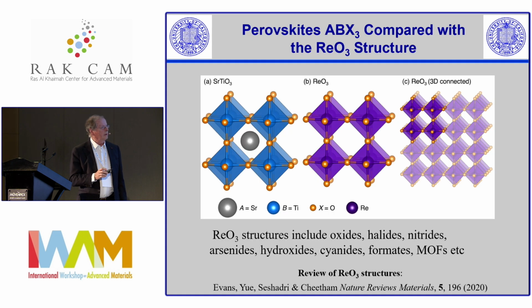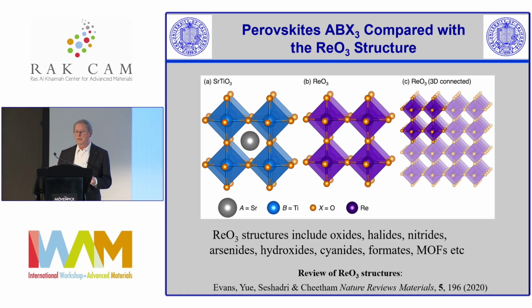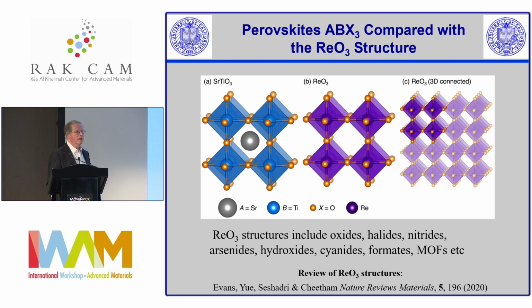So I'm going to switch gear now to talk about the rhenium trioxide type formates, which are a very interesting family. If instead of having, say, an alkyl ammonium cation with zinc 2 plus and the formate linkers in the perovskite structure, we replace the zinc by a trivalent cation, we don't need a cation in the cavity. And so we can go from a perovskite of this type to a rhenium trioxide where there's nothing in the cavity. And this is three connected. And we wrote a Nature Reviews Materials article on these rhenium trioxide structures. They're absolutely fascinating. And of course, Manganese thiocyanate, one of them, belongs in this family here.